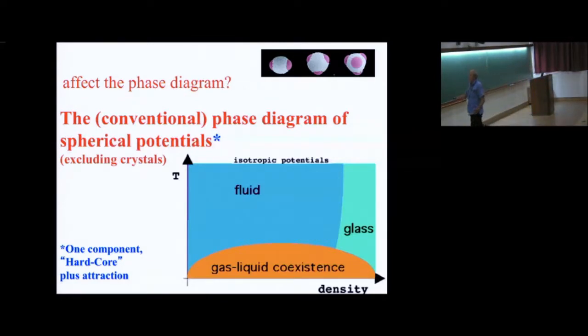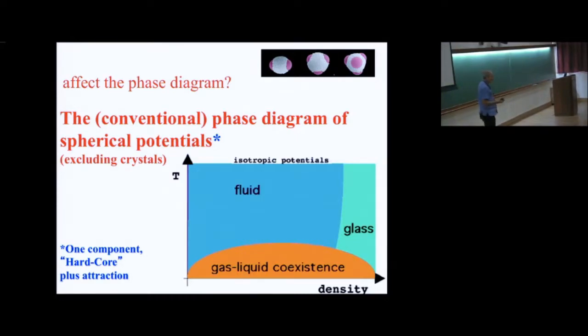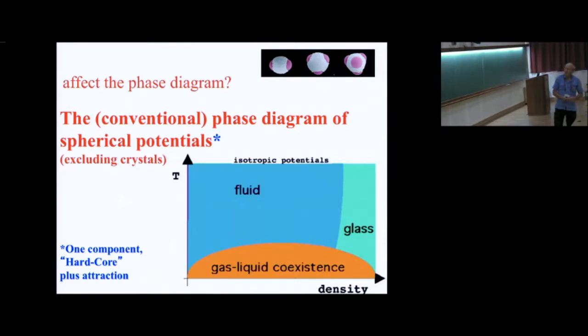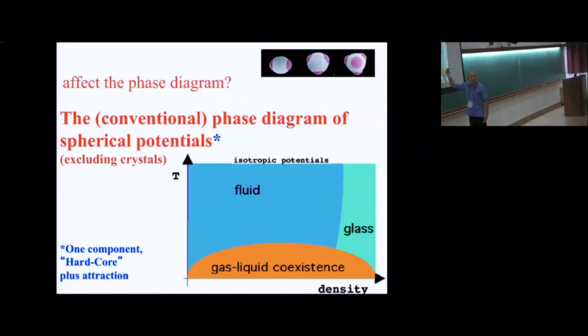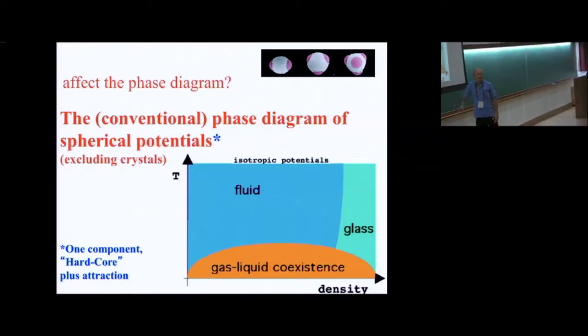But you would like to see what is the lowest temperature that can allow you to form an arrested state. And if you try to do it with a spherically interacting particle, like a hard sphere plus some attraction, you always end up in a gas-liquid phase coexistence. The gas-liquid phase coexistence is very wide. The interaction is isotropic. You know that the particle likes to be surrounded by 12 neighbors. And so the density of the gas coexisting with the liquid usually is very large. It's larger than the density that you would expect for a glass transition.